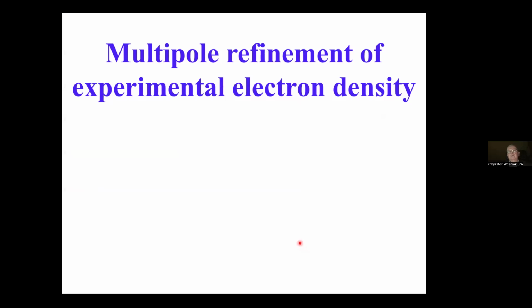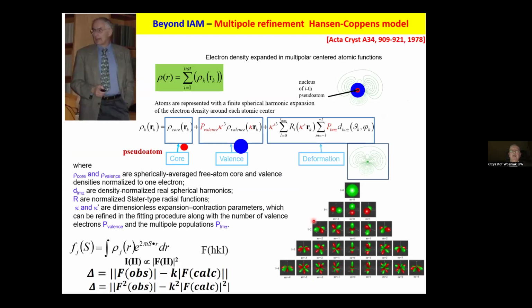So let us now switch over to multipole refinement. Multipole refinement originated from the Frederick Hirshfeld laboratory at the Weizmann Institute in Israel. There are a few different versions, and I will only discuss this one presented in the slide, which is so-called Hansen-Coppens approach, as it was published in this Acta Crystallographica paper. According to this model, electron density in crystal is sum of atomic contributions called pseudoatoms centered at the atomic positions. And each atomic contribution has three terms: spherical core electrons, spherical valence electrons, and so aspherical term, sometimes called deformation term. This spherical core electron term is simply calculated using ab initio methods.